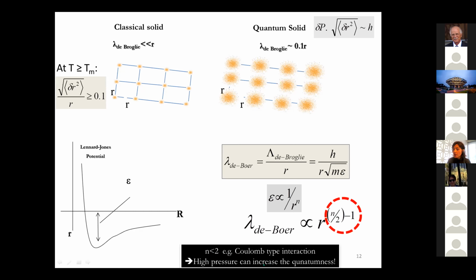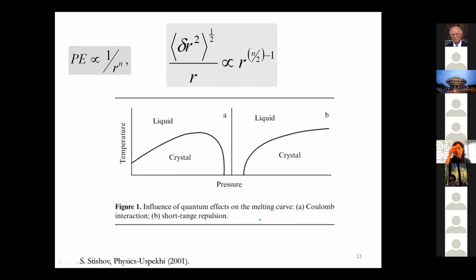So high pressure can be increasing quantumness in specific cases where the potential behaves a certain way. Now, based on that, some years ago, it was proposed that you can have these two classes of melting, basically based on order-disorder behavior. One is the universal one, which is for most things: as you increase the pressure, this is the pressure axis, the disorder becomes less and less favorable, and the material stays in the crystalline phase more and more. And the other one is true for materials that are highly quantum.